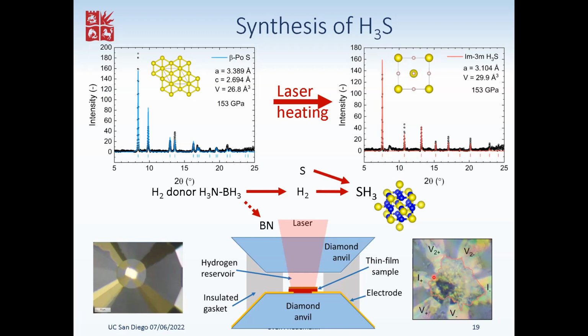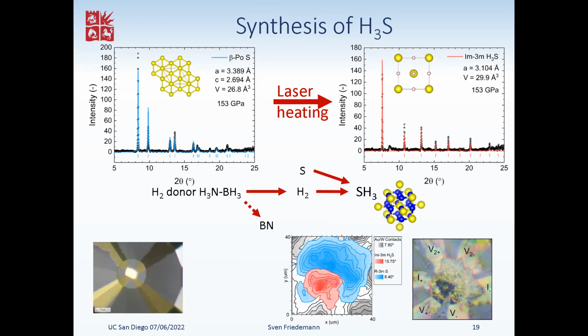The black area is where we've done the laser heating, and the black area is exactly where we observe the X-ray pattern from the H3S. So we can, for instance, take this peak intensity and look at it in a spatial map, and we see this area here in red, which has got this H3S phase, whereas everything else, taking this peak intensity, has got the elemental sulfur phase. So we quite clearly see that H3S is formed here.